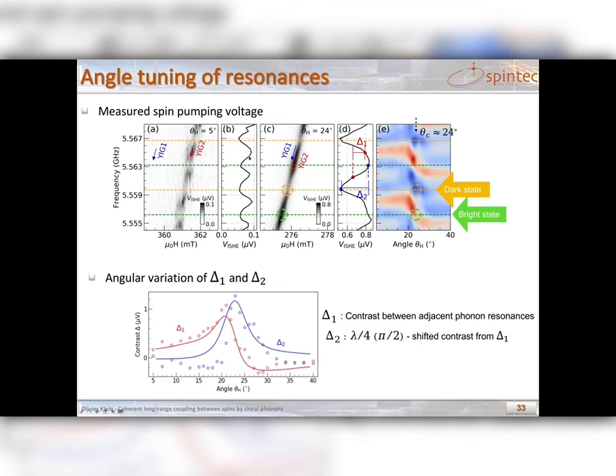We see a similar thing when you do angle tuning. If you start at 5 degrees, where the two Kittel resonances of the bottom layer and the top layer are very detuned, the intensity becomes weaker when the Kittel mode crosses a phonon line. You can also see this in this frequency projection of the intensity. When you move to zero detuning, where Kittel 1 and Kittel 2 are degenerate, the green line becomes a peak and the orange lines become a dip. Or if you want, you have a bright state here and a dark state here.